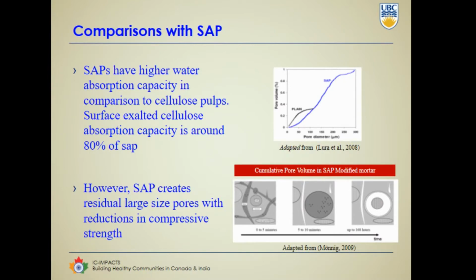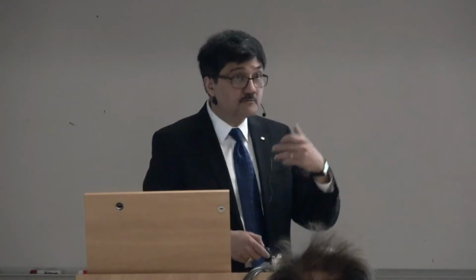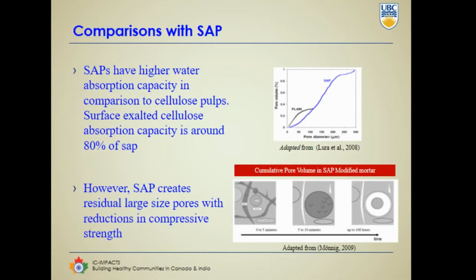One other material which we use is superabsorbent polymers for internal curing. The problem with superabsorbent polymer is that, of course, it absorbs more water than cellulose, but it also leaves a void behind. And because it leaves a void behind when water is extracted from the superabsorbent polymer in the body of concrete, you end up having a loss of strength. Cellulose doesn't do that because it's not creating a void as a result of its water extraction process. And I'll show you that, in fact, you don't get that kind of loss of strength as a result of the desorption in the cellulose itself.